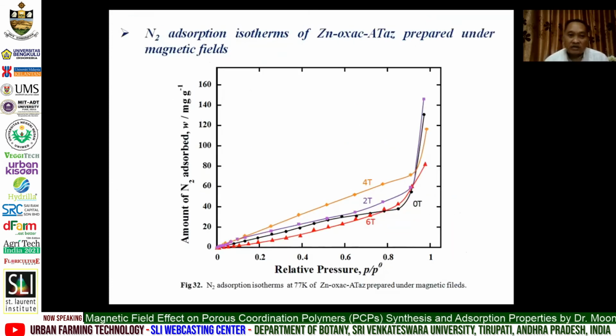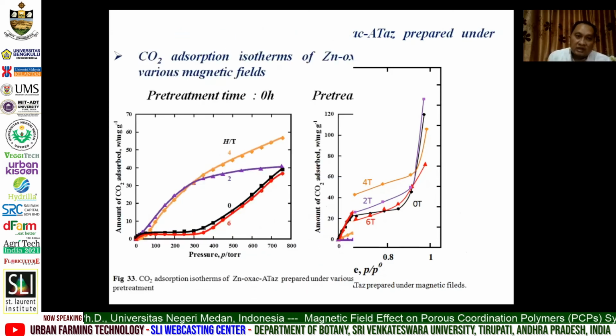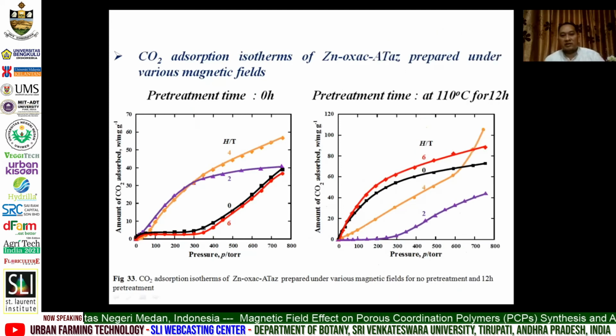And this is the nitrogen adsorption isotherm of zinc oxalate ATaz. So on all the 0 Tesla and magnetic field crystals, it cannot adsorb nitrogen gas. It suggests that pore formation is disturbed by the presence of the amine group inside the pore. But interestingly, for CO2 adsorption,